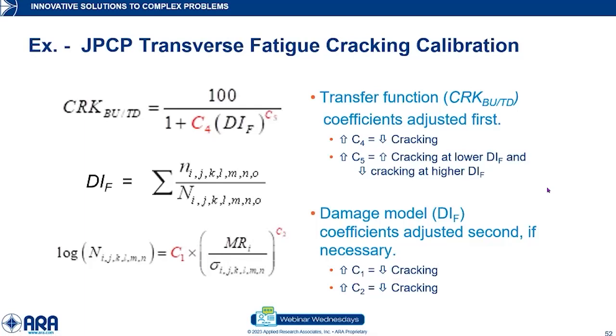And I don't want to bore people with showing equations here, but just to show you real quickly what's happening. You normally start with the transfer function itself, adjust those coefficients. And you can see here by increasing, we have a C4 and C5 coefficient. This is the cracking combination of bottom up and top down fatigue cracking concrete. And by increasing it, it has various effects on the cracking prediction. If you can't tweak the model enough doing this to lower your standard error and bias enough, then you go to the damage model and you adjust those coefficients. And again, you could see the impact of, in this case, increasing either of those coefficients.